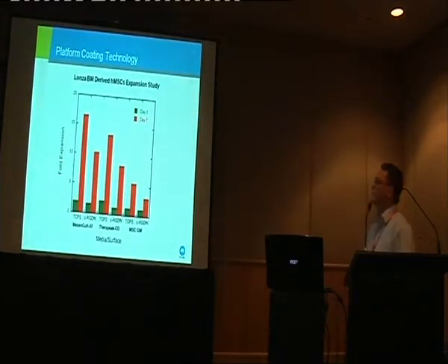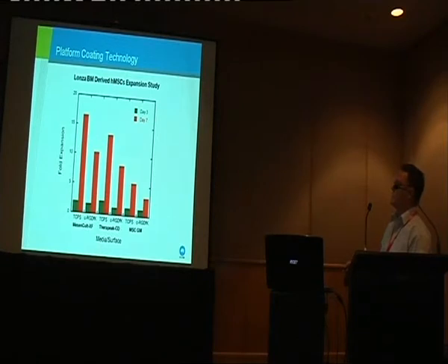When you look at the growth rates as a fold expansion, you can see that the mesenchymal media gives the highest fold expansion rates, and what should also be obvious is that, again, we see this 60% reduction in the fold expansion of the cells. We haven't fully analysed the markers to know whether the markers are retained preferentially on the synthetic surfaces, but that data will be coming soon.